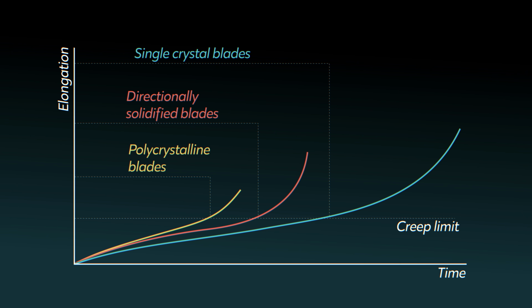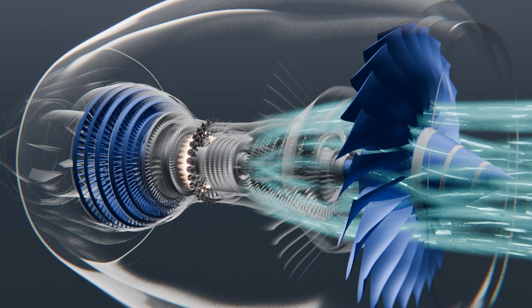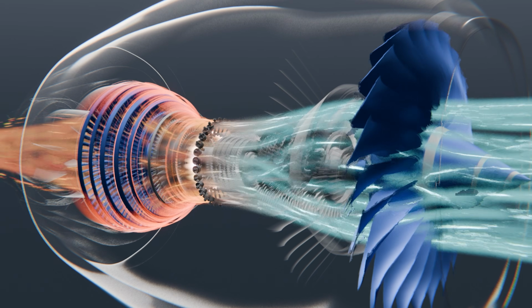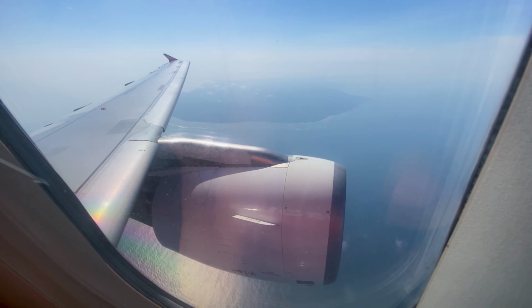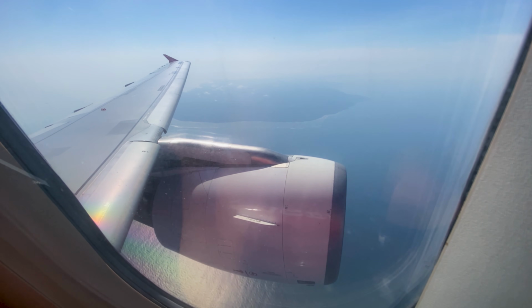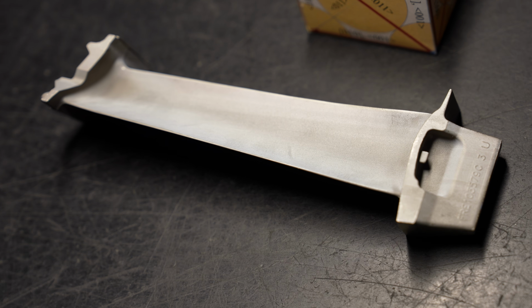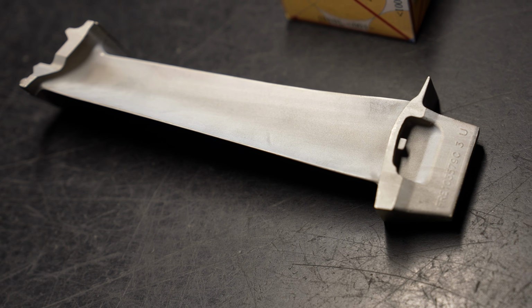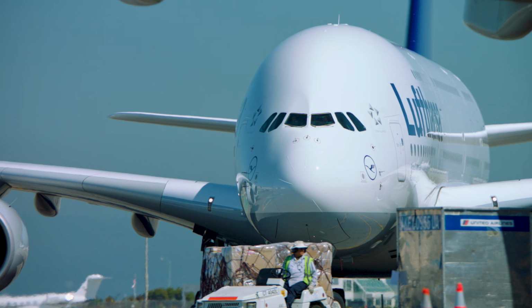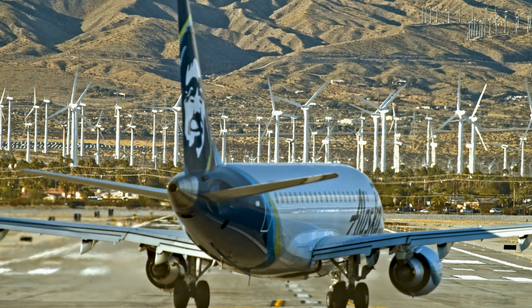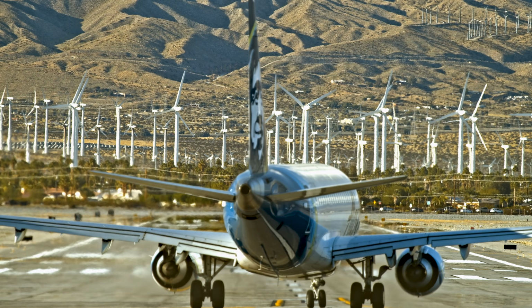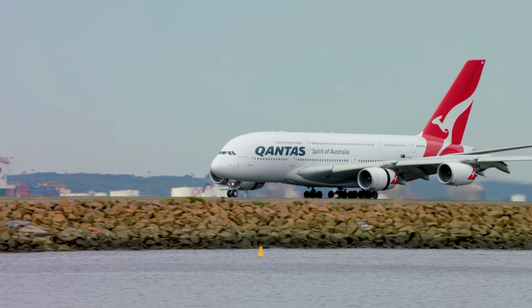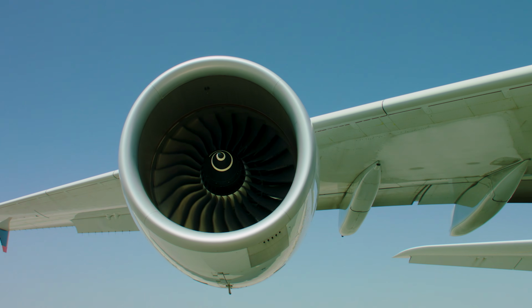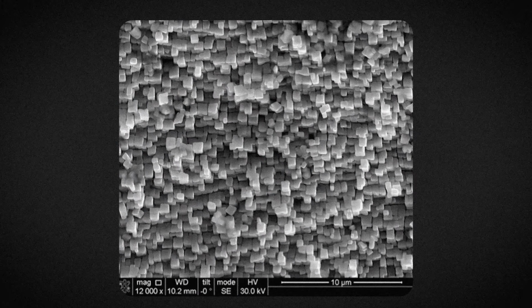They last up to 9 times longer against creep and thermal fatigue, and are more than 3 times more resistant to corrosion than blades made from multiple grains. That's why modern jet engines can now run for 25,000 hours between major overhauls, something that would have been unthinkable before single crystal blades. And the impact has been huge. Between 1960 and 2010, jet aircraft became about 55% more fuel efficient. And a huge part of that improvement comes down to advances in these nickel superalloys.